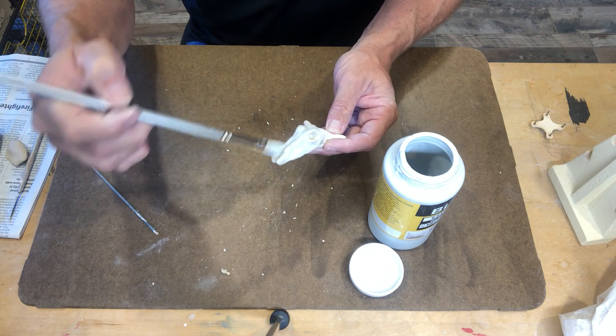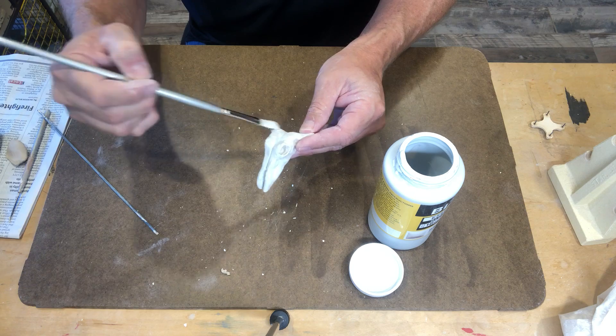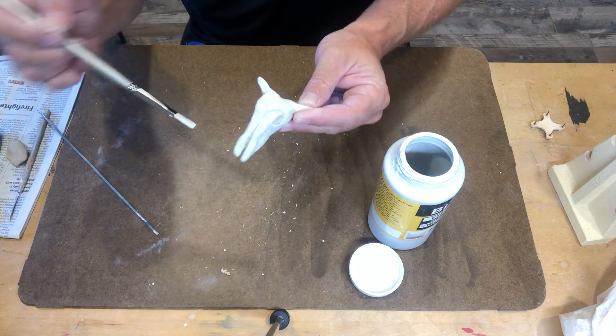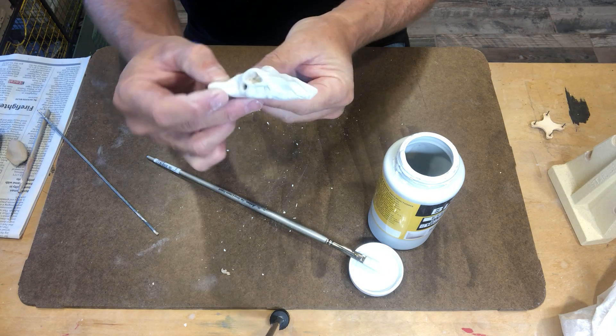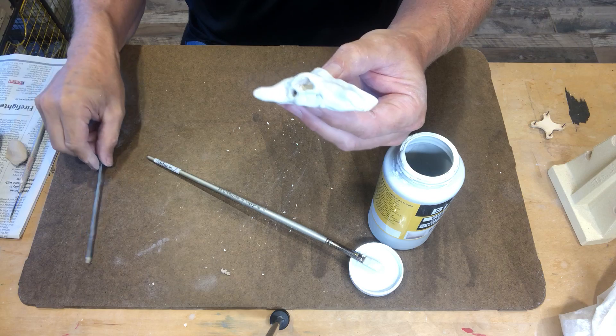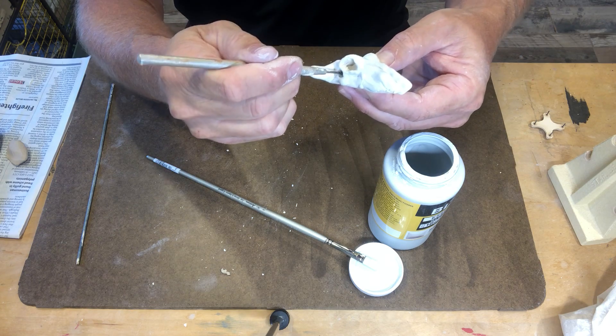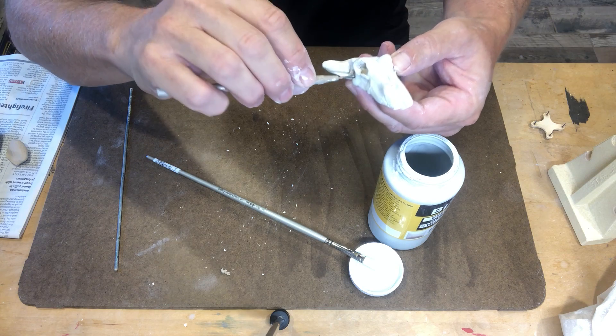We're going to put on three coats of glaze. Before doing the bottom, make sure the top is glazed and dried first — it dries pretty quickly so you have to be a little patient. One thing to be careful about: inside the hole where the bead bar goes, there can't be any glaze. If there's glaze in there when you fire it, it'll stick to the bead bar and be hard to remove. So use your needle tool to scrape out any glaze inside that hole.